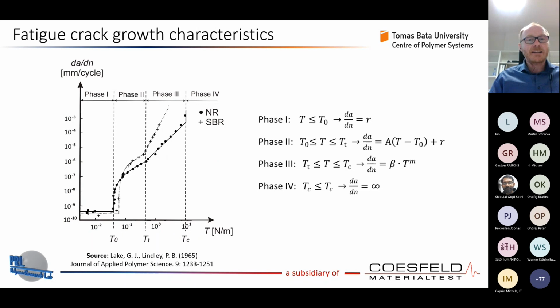I will go into more detail regarding this characteristic. We can divide it into 4 different phases. Firstly, there is a region where no crack initiation and crack growth occur. Mainly there are some issues with ozone and chemical problems. However, no crack initiation. Then at T0, which is the intrinsic strength, the endurance limit, the crack is initiated. We need to understand that crack initiation means that there is a crack in the rubber material. However, this crack doesn't propagate. Only when we are over the energy associated with T0 is the crack initiated and does it propagate. This we need to fully understand.